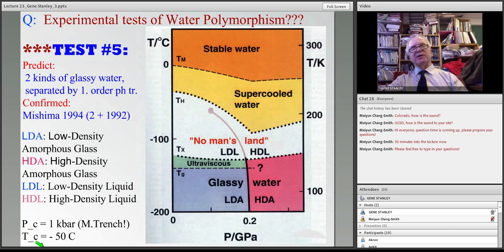Okay, now, simulations is one thing, you get out what you put in. Experiment is something else. So let's turn to experiment for most of what remains in this lecture. The very first experiments were done just 2 years after the Poole-Sciortino work by the father of amorphous solid water, Mishima. And what Osamu Mishima found was that if he went to glassy water and pressurized it, he could undergo a first-order transition to a different form of amorphous water called high density amorphous water, and furthermore it was reversible. He could relax the pressure and he would go back to regular. So he found 2 well-defined, experimentally well-defined phases of amorphous water.